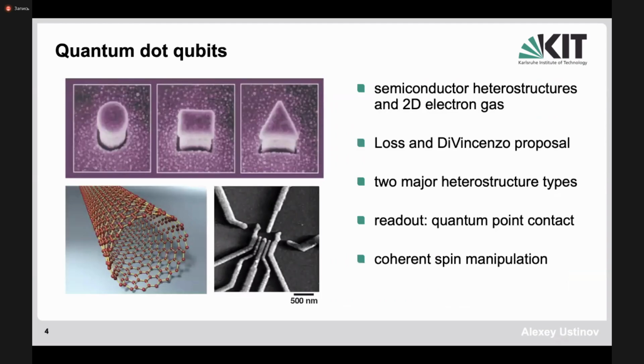Quantum dots. When you read the term quantum dot, then different people think of different things. So there are, for example, this type of devices which have a size of a few nanometers, a few tens of nanometers, a few hundreds of nanometers. These are so-called self-assembled quantum dots, which grow from gas phase on the surface of a pristine semiconductor surface, and then they form naturally a kind of box for electron states, and then electron quantization in a box leads to discrete energy states, which are then forming the eigenstates of the dot.